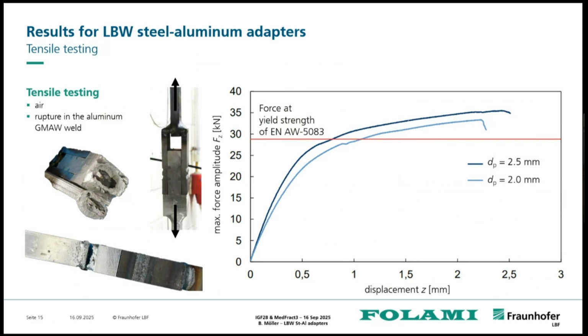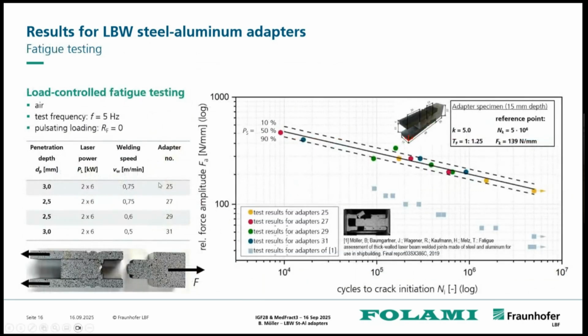Not just therefore, but also due to this reason, we went over to fatigue testing. In this case, load controlled fatigue testing, with the actual force as it was more or less in the tensile test as well, on the aluminum side and on the steel sheet side. And we included the parameter variations shown before as well. So different welding speeds here, leading to different penetration depth of the local weld geometry, and finding more or less the same as we had for these cross-beam specimens: within the scatter, these parameters do not give a trend towards one of the welding speeds, for example.